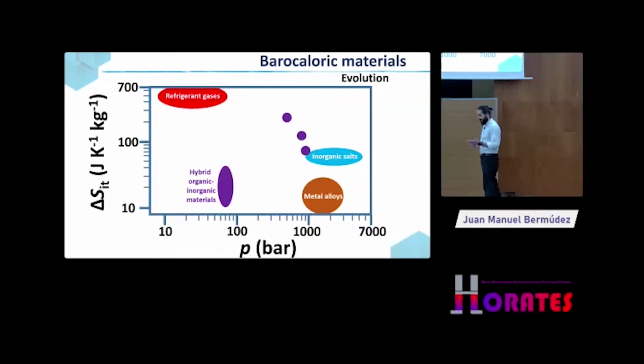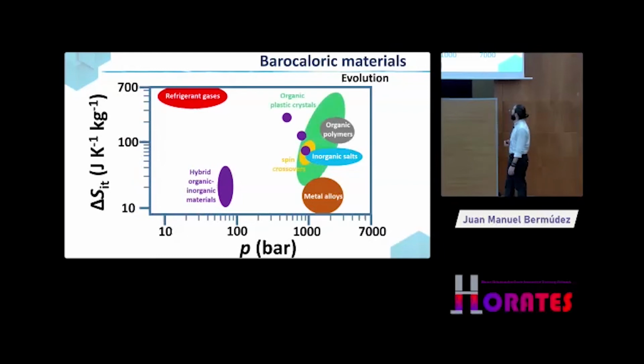Then other families of materials started to be explored for barocaloric purposes. As I said, that is a very young field, so people have been incorporating into the field in the last years. They have studied organic polymers, which are quite promising, but still the pressures are quite high. Then spin crossover materials, where you can induce the spin transition with pressure, also very promising, but still at high pressures. And one really interesting family is that of organic plastic crystals, where you have a transition between a crystalline state and a plastic state that can be reversible. They manage to reach entropy change values very near or similar to the refrigerant gases, but still you have to apply a very large pressure.